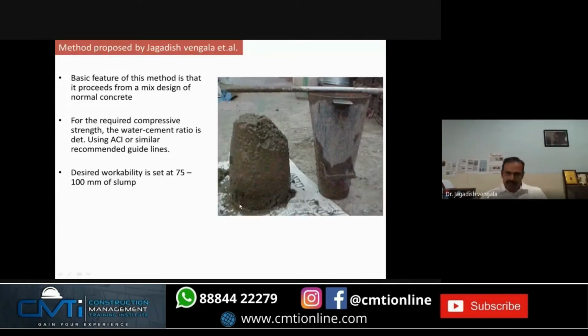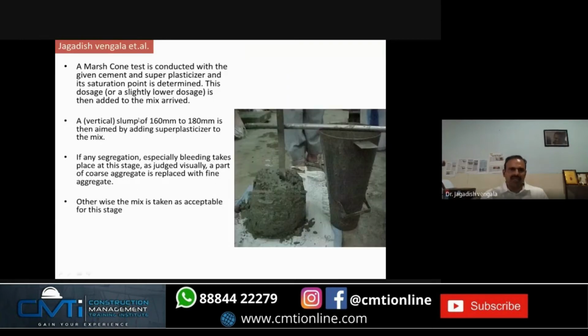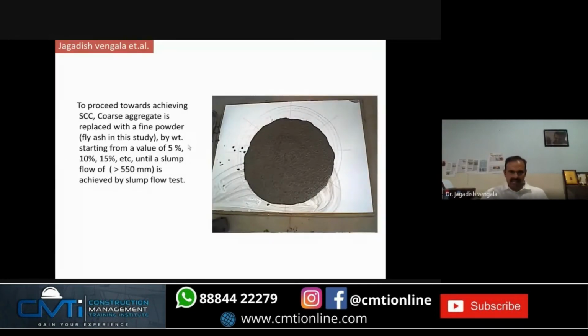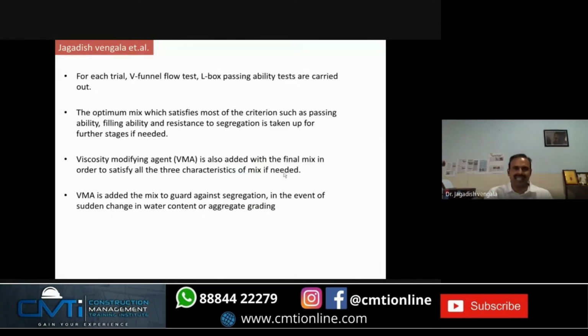So in my method, like normal mix design, once you do it, you achieve a workability of 75 to 100 for normal concrete. After that, because we have more coarse aggregate in normal concrete, you replace the coarse aggregate using fly ash in various percentages, 5, 10, 15, and slowly you achieve the self-compacting concrete. Replacing coarse aggregate with fly ash or any other cementitious material will give you flow to the concrete. At the same time, you have to conduct other tests like V-funnel, L-box, and other things. And VMA will guard against segregation, because we usually observe a change in water content due to aggregate moisture and other problems, and even grading problems.